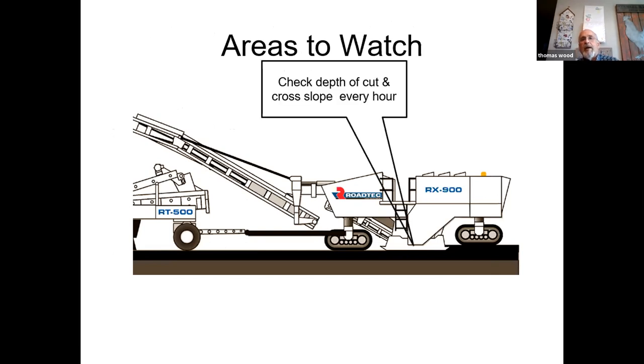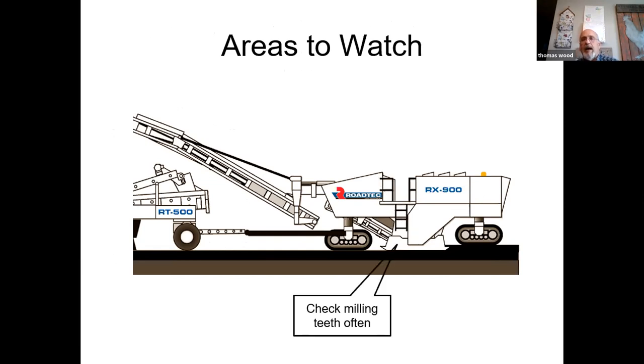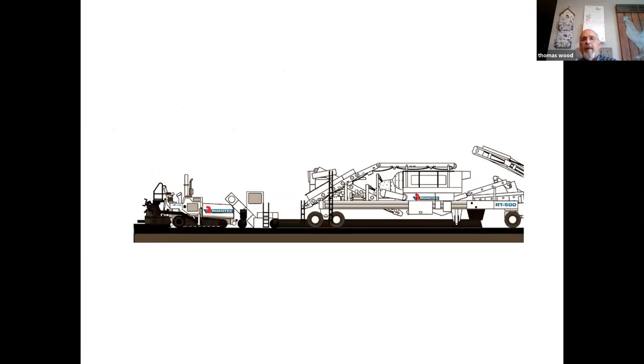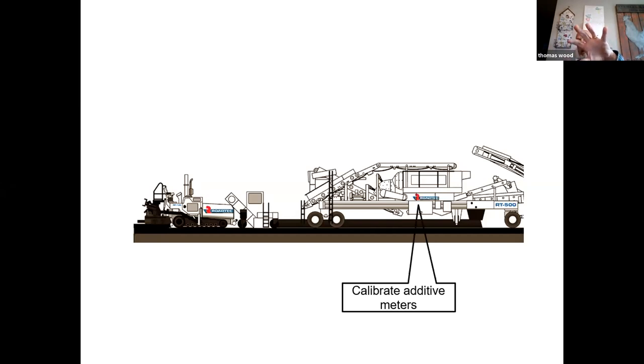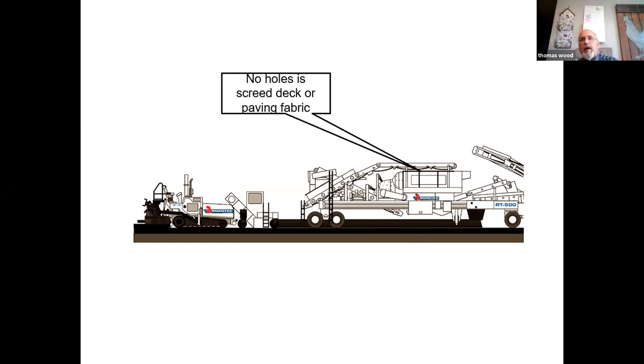So back to the Roadtec: check the depth and cross slope at least once every hour. Here on the screening plant, calibrate additive meters, make sure that the belt scale is calibrated and everything is putting the right amount of material in, because you went through all the expense of doing a mix design. And if your belt scale is off or your metering system's not working right, you really don't know what you're doing. No holes in the screen deck or paving fabrics.